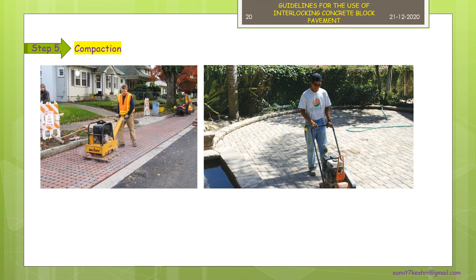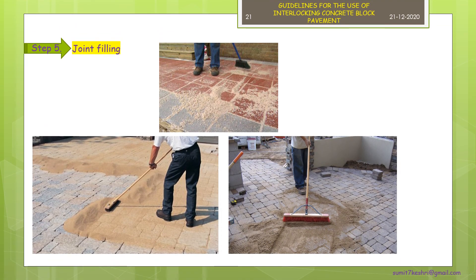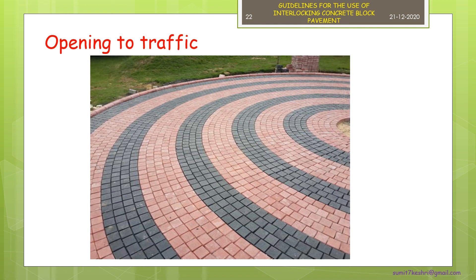For compaction of the bedding sand and the blocks laid over it, vibratory plate compactors are used over the laid paving units. At least two passes of vibratory plate compactors are needed. After the compaction of the bedding sand has been completed, the joints should be completely filled with sand meeting the desired specification. The process of joint filling comprises of spreading a thin layer of joint filling sand on the block surface and brooming the sand into each joint. The best advantage of block pavement is that it does not require any curing time, and traffic is opened soon after the work is completed.